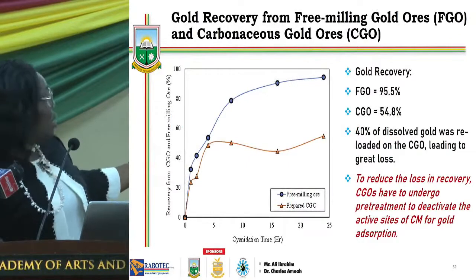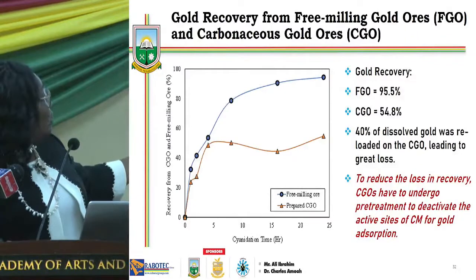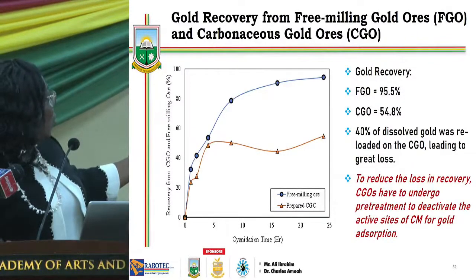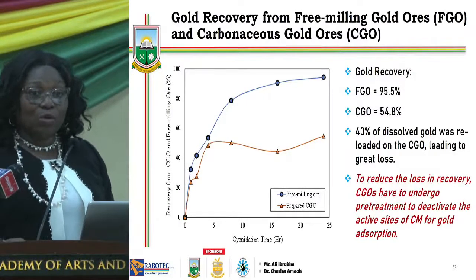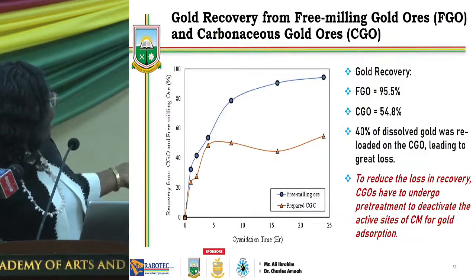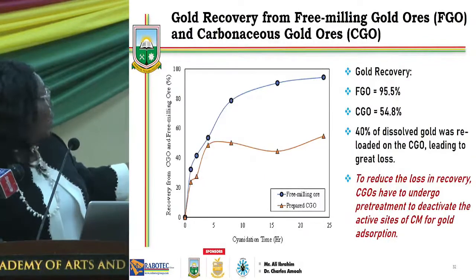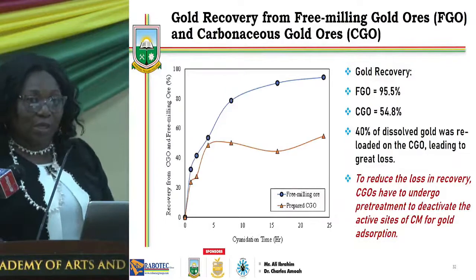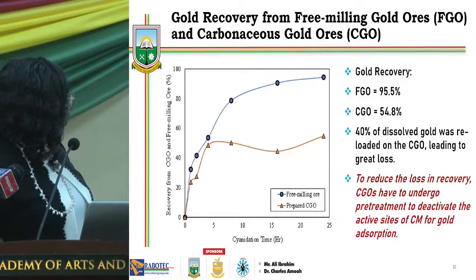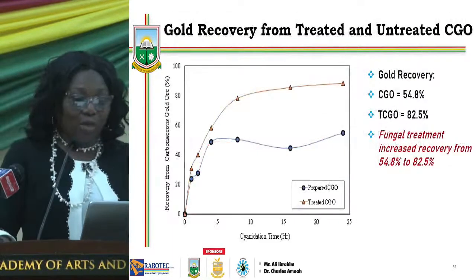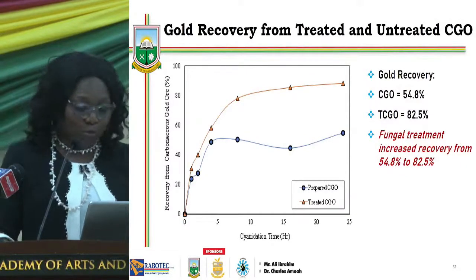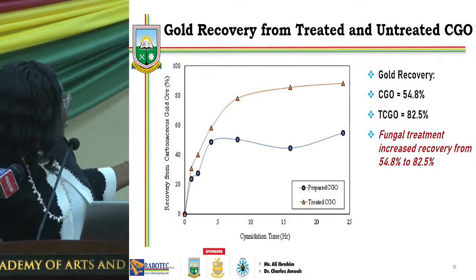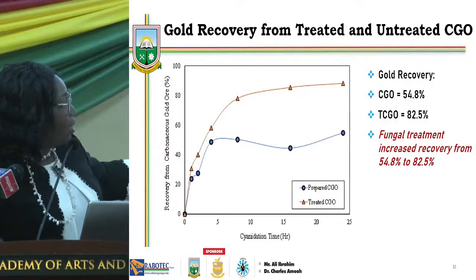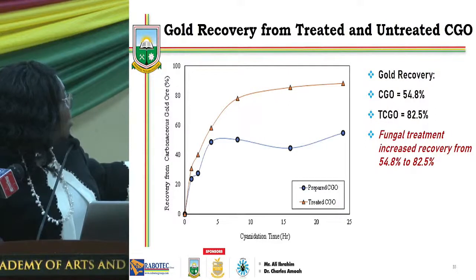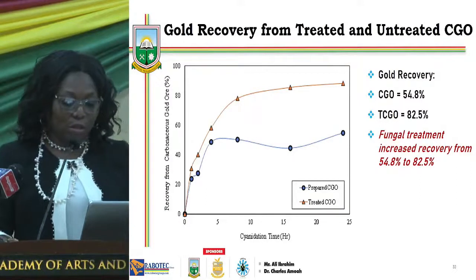So the blue line is showing us the free milling gold ore, and obviously giving us a recovery of 95.5%. When the free milling ore was dosed with 3% anthracite, it became carbonaceous ore, and that is a high-grade carbonaceous ore. And when it went through cyanidation, the recovery was 54.8, about 40% decrease because of 3% carbonaceous material. Now, the carbonaceous material surrogate was treated with Phanerochaete chrysosporium. And after cyanidation, the yellow line is showing us the carbonaceous gold ore that has been treated. And that gives us 82.5% recovery, as against 54.8% from the carbonaceous gold ore.